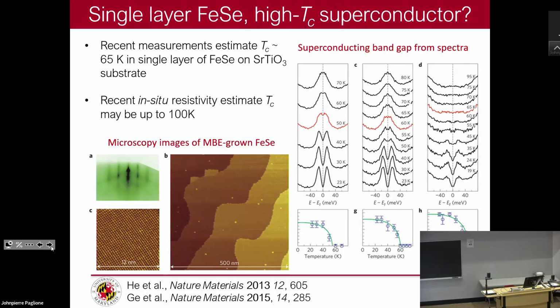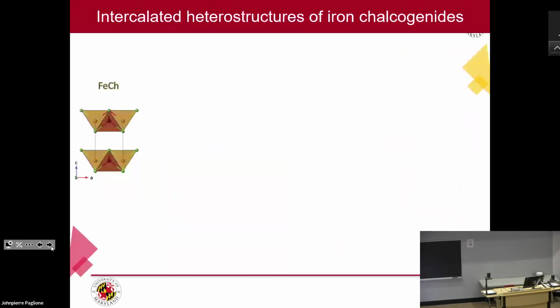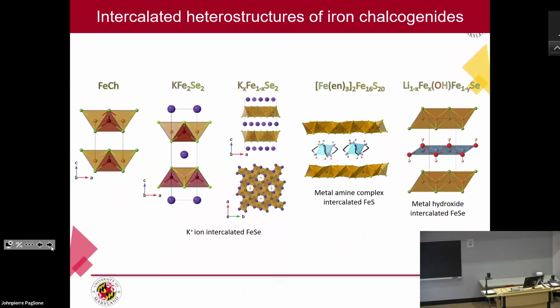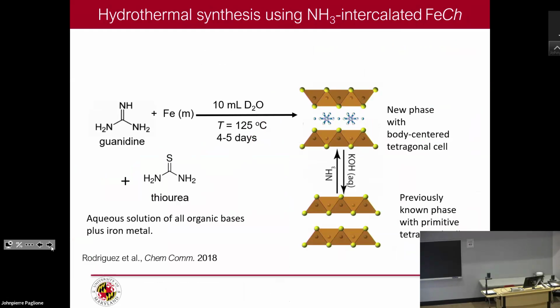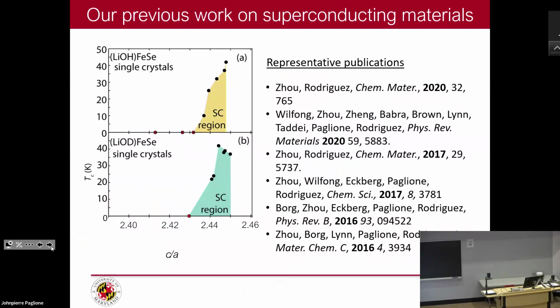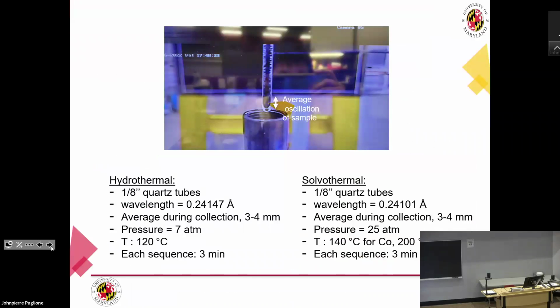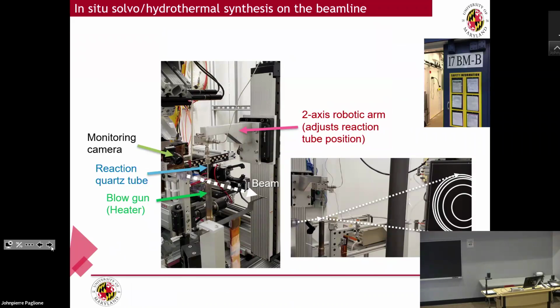One of the things that still intrigues me about iron selenide as a superconductor is that there have been reports where they put iron selenide on strontium titanate and say that they have 100 K critical temperature, maybe 65 Kelvin is probably the more settled number. And so what's nice about iron chalcogenides is that you can fill them in with all kinds of ions, molecules, or layers. And so you can do this through hydrothermal methods. In the interest of time, just to understand those hydrothermal methods, sometimes it's very difficult to know what's going on.